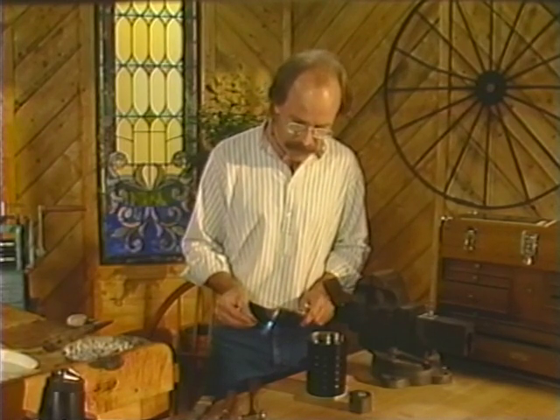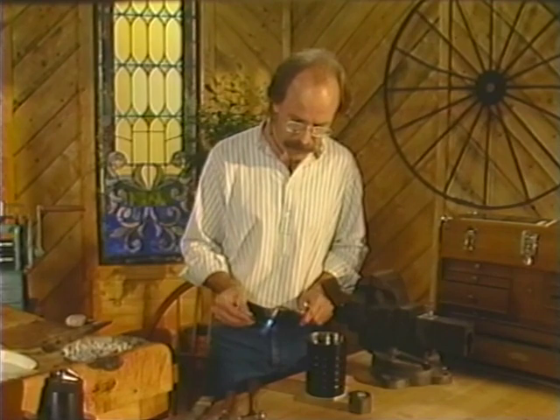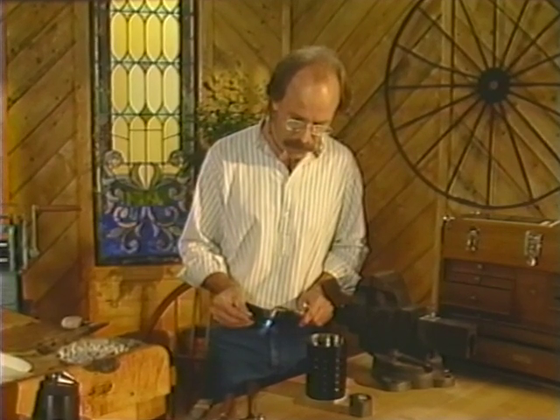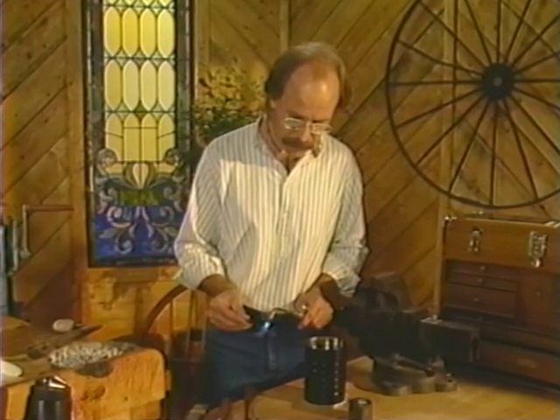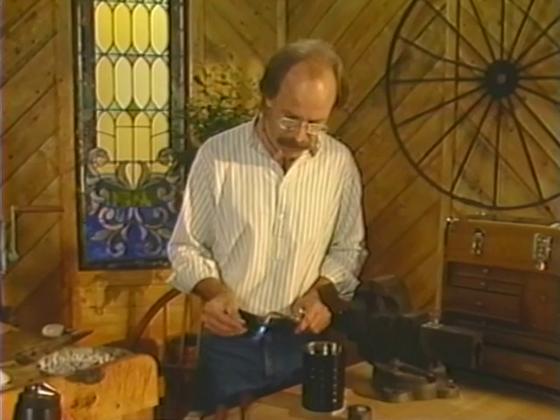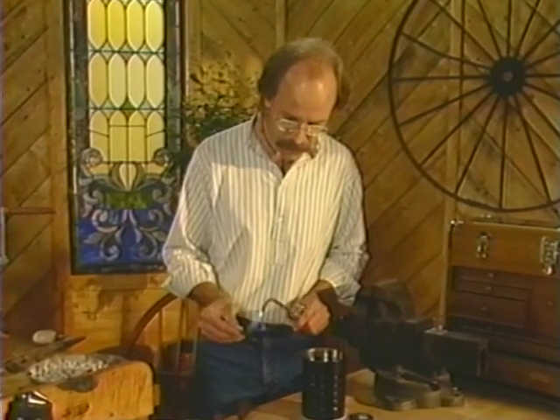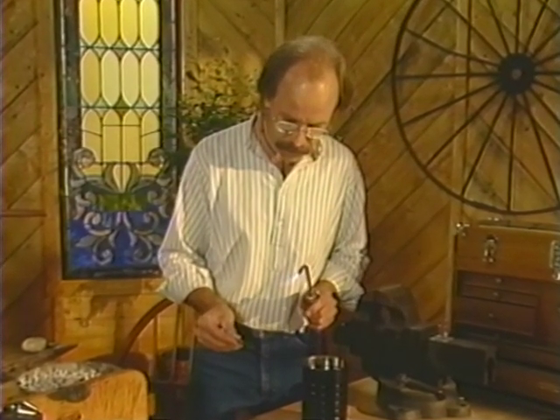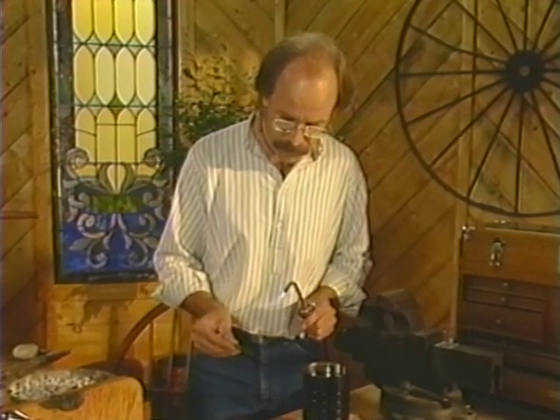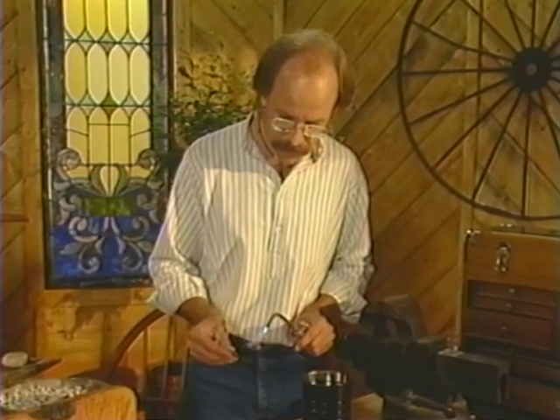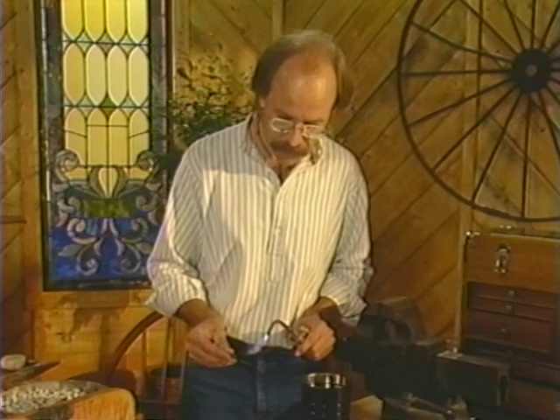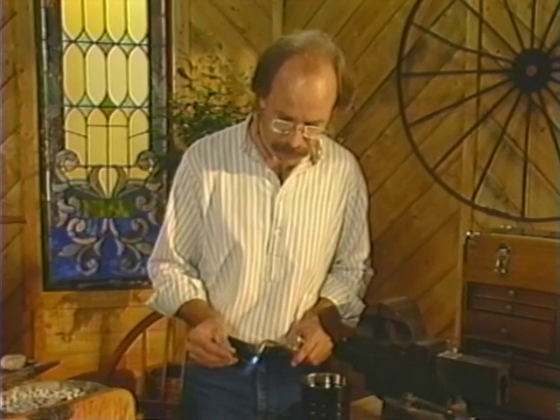Last time I moved the flame around, this time I'm going to keep it constant, about an inch and a quarter, inch and a half away from the tip. Nothing's going to happen for a few seconds, and then you're going to see a rainbow of color. There it is. You see blue in the center, next to it is plum, followed by brown, followed by a straw or bronzy yellow. It's that bronzy yellow that I'm going to watch.